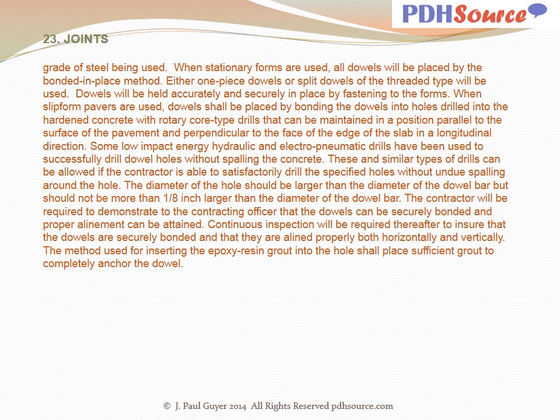The diameter of the hole shall be larger than the diameter of the dowel bar, but should not be more than 1/8 inch larger than the diameter of the dowel bar. The contractor will be required to demonstrate to the contracting officer that the dowels can be securely bonded and proper alignment can be obtained. Continuous inspection will be required thereafter to ensure the dowels are securely bonded and that they are aligned properly both horizontally and vertically. The method used for inserting the epoxy resin grout into the hole shall place sufficient grout to completely anchor the dowel.